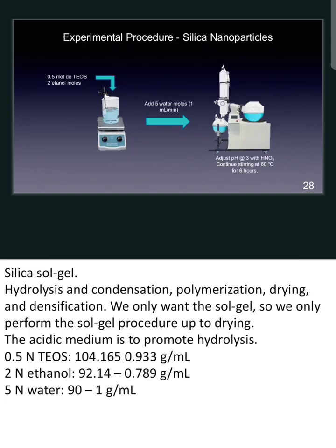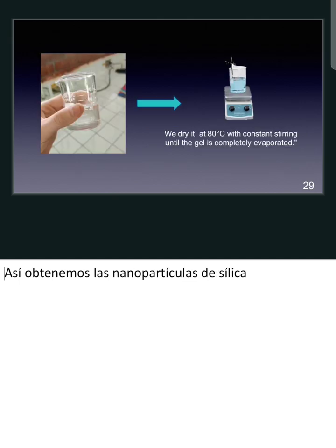Talking about the stabilization method, first we need to make silica nanoparticles. We add 0.5 moles of TEOS, 2 ethanol moles, during stirring, and then while they are stirring, we add 5 water moles at 1 milliliter per minute, and then after that we adjust the pH to 3 with nitric acid, and we continue stirring at 60 degrees for 6 hours. And then we have our gel. However, we also have to dry the gel in order to obtain only the silica nanoparticles.